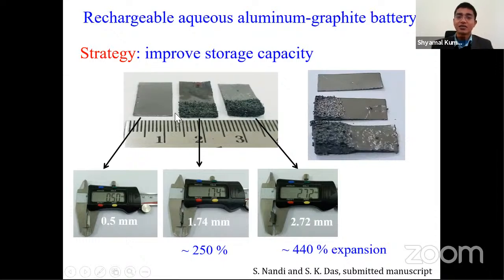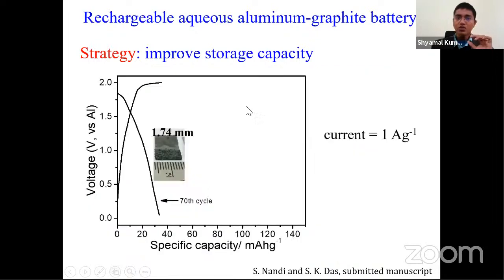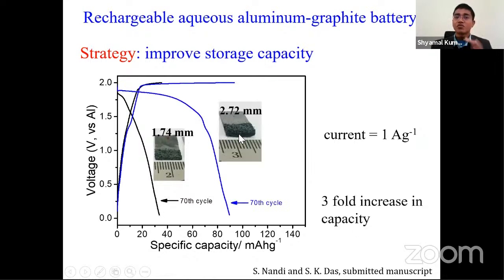As you can see in this figure, this is very, very thick graphite foam. When we use this graphite foam, this is the initial experiment. We could achieve 35 milliamp hour per gram. When we use this highly thick graphite foam, we could dramatically improve the number. There is a 3-fold increase in the capacity. Not only that, we could get a very stable discharge plateau, or say cell voltage, on a battery.